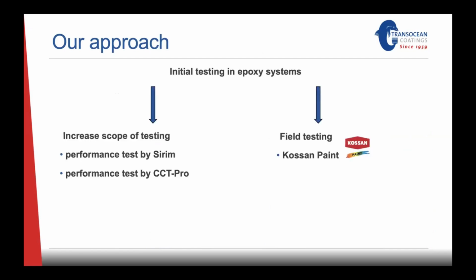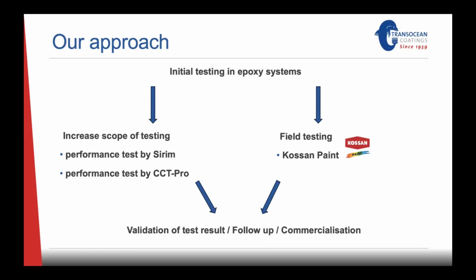Transocean Coatings. So our approach was, okay, let's do an initial start in several epoxy systems. From there, we saw some influences, we got test results, and we had a two-way approach. One is that we increase the scope of testing, which I will show you in the next slides. And then at the same time we start field testing in collaboration with Kossan Paint. Then finally, we end up with the validation of the test results, the follow-up, and the commercialization of products.